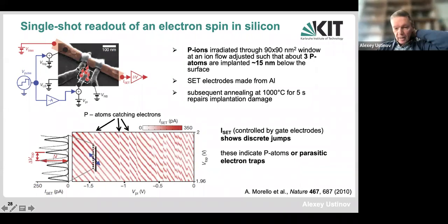So this is the device which was fabricated in the lab of Andrea Morello in Australia more than 10 years ago, which actually made it possible to perform a really unique experiment. As you see, these people have been working on Kane's proposal for more than 10 years. So what they've done, they covered the silicon chip by a protection layer, and then irradiated the whole sample with high energy phosphorus ions. In this dashed rectangle, they had a small opening of about 90 by 90 nanometers. And according to the flux of phosphorus, they were expecting to have about 3 phosphorus ions in the small area. In the rest of the circuit, there were no phosphorus ions implanted.